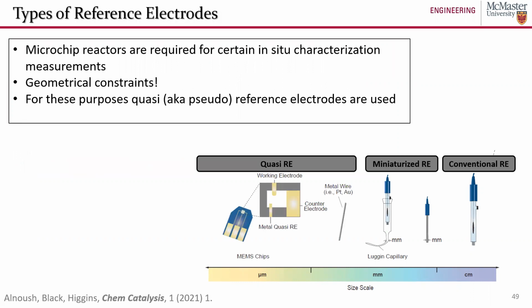And these may be experiments where we require microchip reactors for certain in situ characterization measurements. Particularly, the ones that we work on are transmission-based measurements, for example, transmission electron microscopy. The reason we need these microchip reactors is because if we have too much electrolyte, we're never going to be able to get enough X-rays or electrons in and through the sample to our detectors. So we need small reactors where we have only a couple hundred nanometers of electrolyte. And the only way to reliably do that is with these microchip reactors.